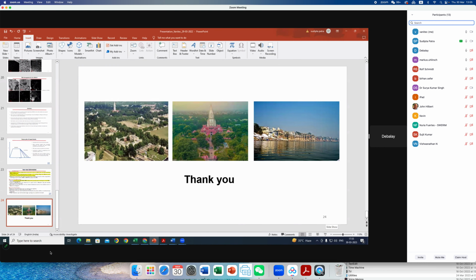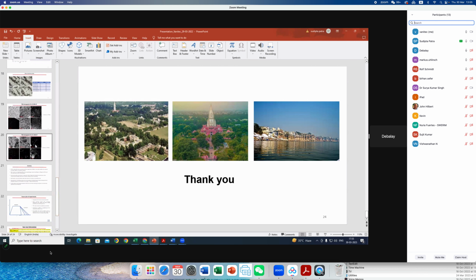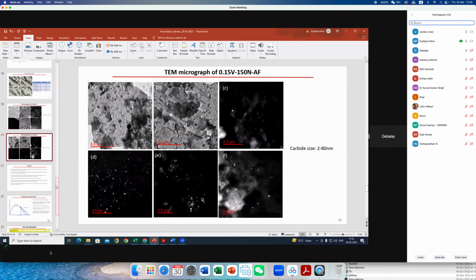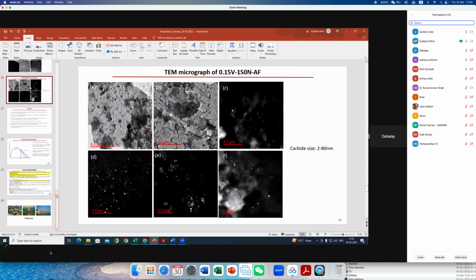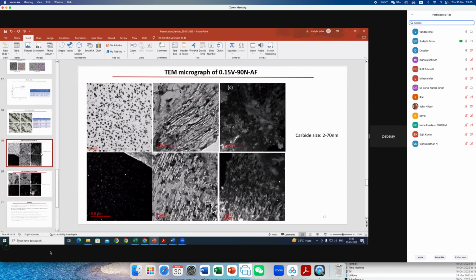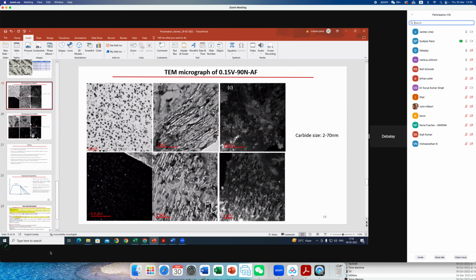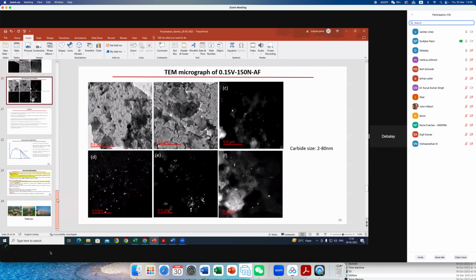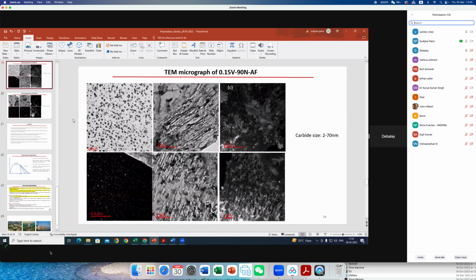Yes, Dr. Patra, nice presentation. As we were discussing, since you were normalizing at 900, it's very important, and Dr. Dev and other experts may also comment, whether the pre-existing precipitates are dissolving or not. The ideal situation would be if, in the pre-existing hot forged condition, whatever precipitates are there, we can dissolve them and then fresh precipitate can form, then strength is expected to go up. Otherwise, if they are not dissolving, then that will control the grain size, but strength may not be that high.